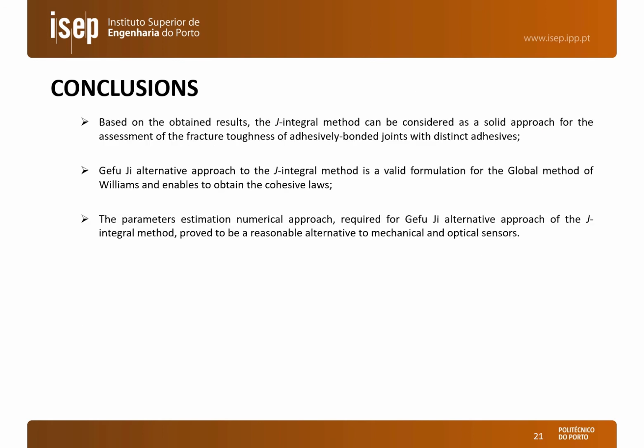And finally, we draw some conclusions regarding this work. We can say that based on the results that we present here, the J-integral method is a solid approach to obtain the G1 and G2 of adhesive joints in mixed mode for different adhesives. We tested two different formulations, the formulation of G and Williams. The J-integral formulation is a valid approach, and since it is based on the J-integral, it also allows us to obtain the cohesive laws, which is a major advantage if you want to make strength predictions based on cohesive zone modeling, for instance.